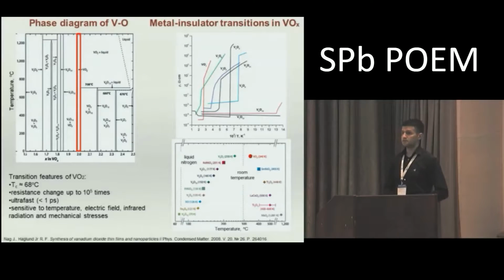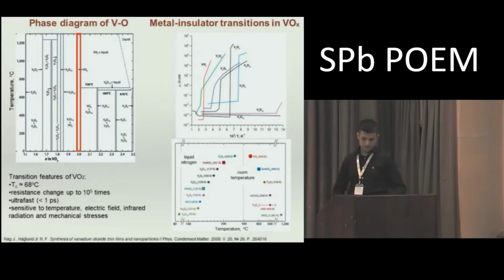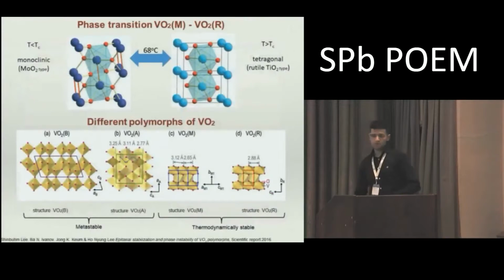Other oxides that vanadium can form with oxygen have their own metal-insulator transition at a different temperature and with different resistance in the low temperature phase and the high temperature phase. It is well known that the phase transition of vanadium dioxide is a first-order transition, and at room temperature the crystal structure is monoclinic. At high temperature we have a rutile type of structure with metal-type conductivity.